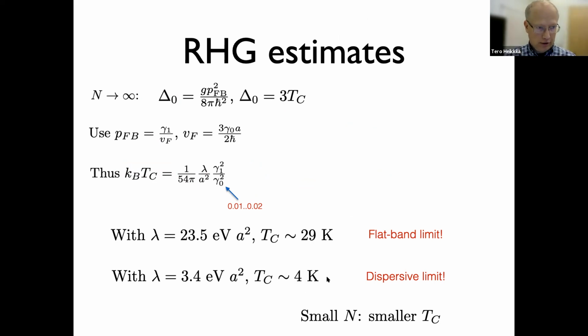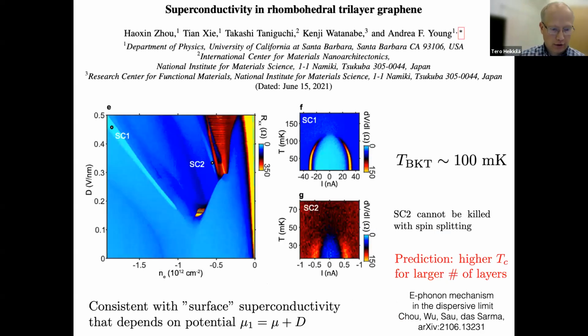So sort of, and we probably are rather here than here. So now that we know the sizes of the couplings pretty well, we can estimate this rhombohedral graphene should have a few Kelvin TC. If you take a smaller number of layers, like 3, you are expected to get a smaller TC. And this is actually what happened.